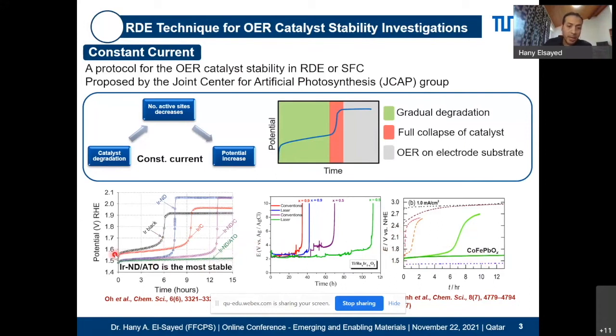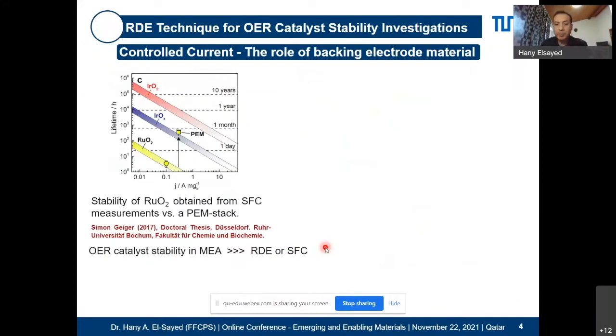You apply a constant current, and whichever catalyst degrades faster, you will see that it goes through this sudden increase in the potential first, and the most stable catalyst will stay there for a longer time, or at least it will make this potential jump after a long time. Well, the problem with this technique is that we don't really think that this is what is really happening. Why is that? Because there's another group here in Germany, in a small city called Erlangen. What they found is that if you use this technique and you try to predict the lifetime of a catalyst using a rotating disk electrode, I'm talking about an OER catalyst, so a gas-evolving electrode.